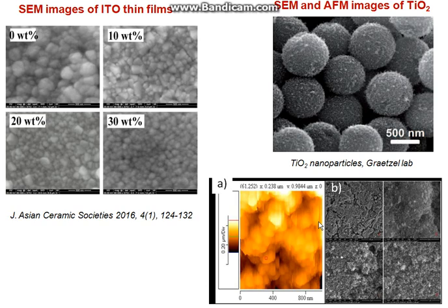Moving on to the right of the slide, this image on the top here is the SEM image of titania from the Grätzel Cell Lab. As you can see, titania nanoparticles in the form of spheres, about 500 to 800 nanometers in size. And these two sets of images over here are AFM and SEM images of titania nanomaterials in the form of films. The point I'm trying to make here is that depending on the fabrication technique, the same nanomaterial can be obtained in different morphologies, different structures, and so on and so forth.